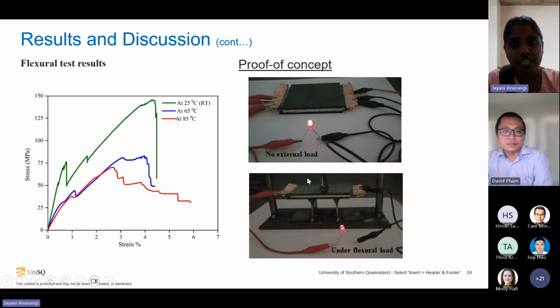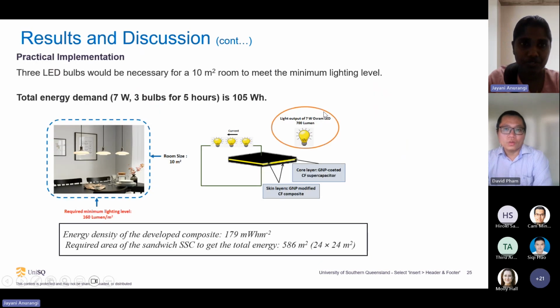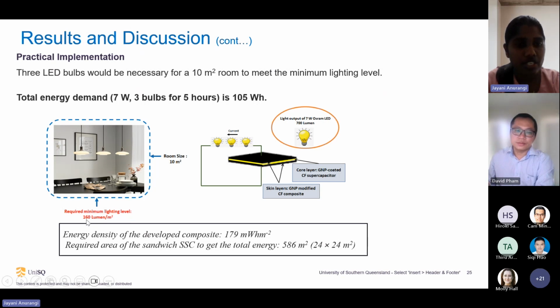As the proof of concept, I powered an LED bulb without external load and with the external load. Actually, in this experiment, I was able to light the LED bulb for more than 10 minutes with this small sandwich composite. As the next step, I evaluate the potential of the developed sandwich panel in real world applications. For that, I calculate the area of the panel required to light a typical 10 square meter room. Typically, the lighting level requirement for a room is 160 lumen per square meter. If the room size is 10 square meter, that means it needs 1600 lumens.